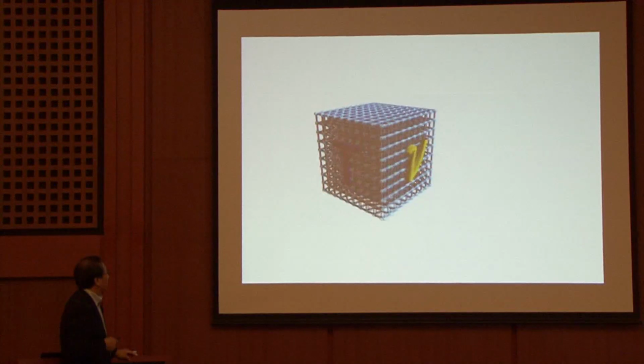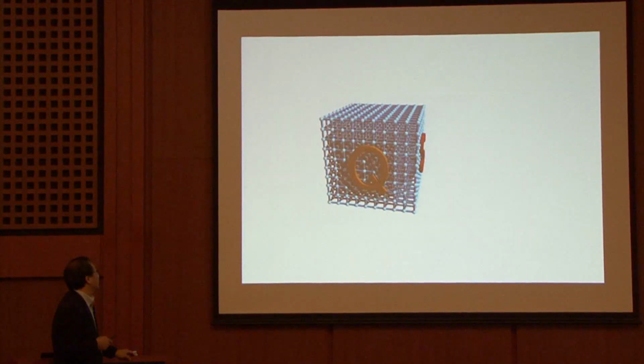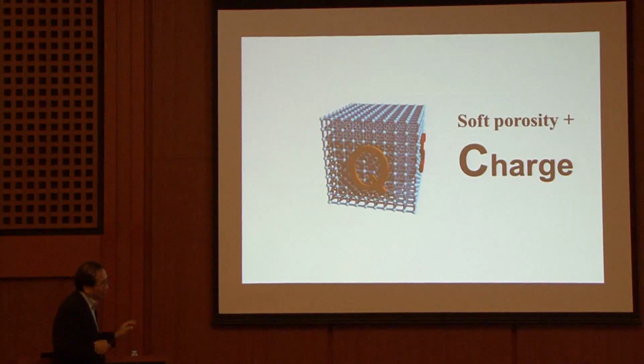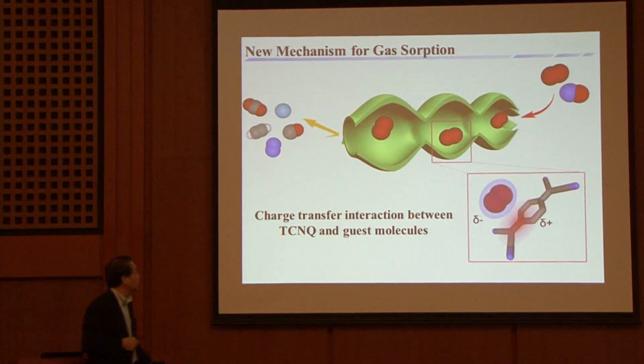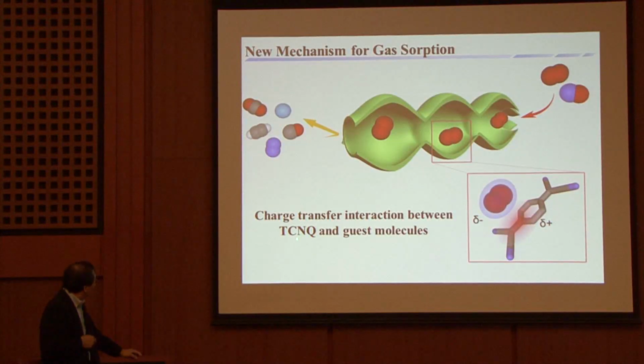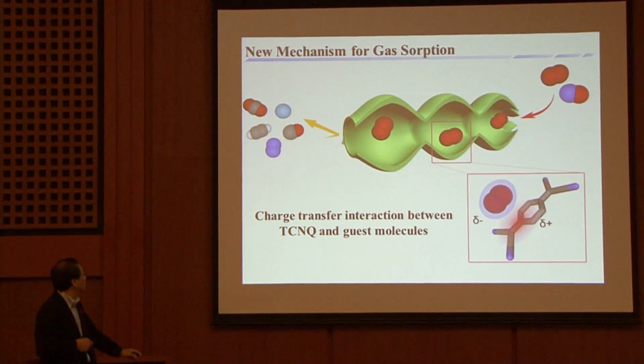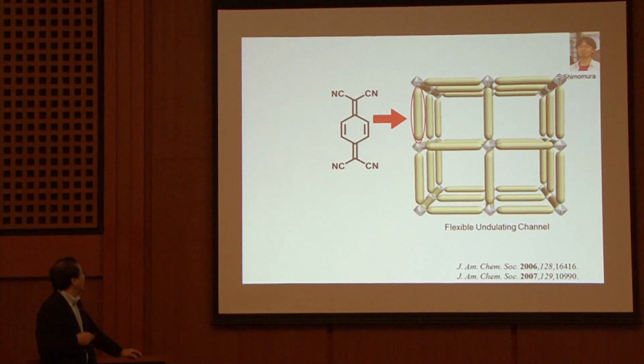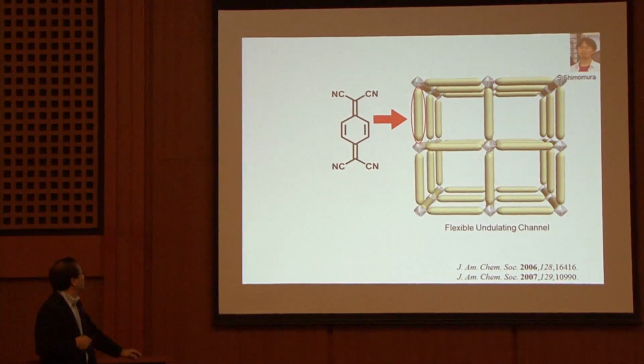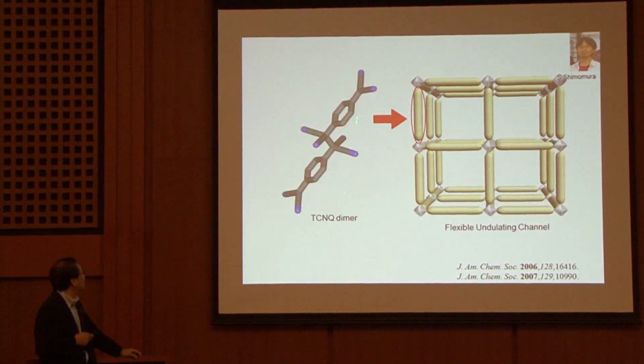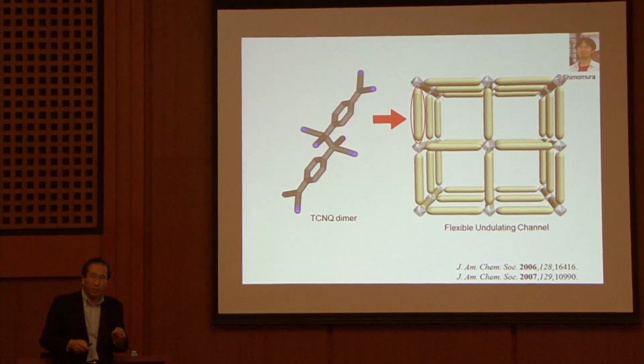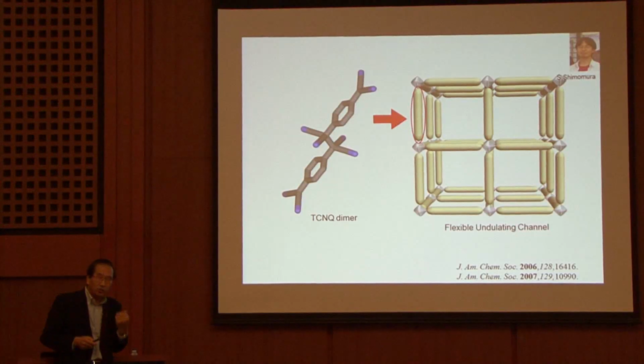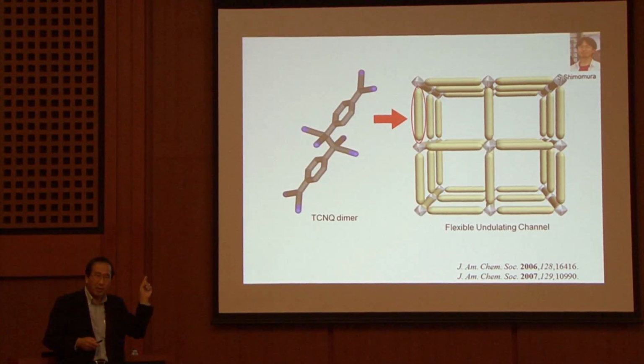The keyword is the charge. That is very interesting. And so let's go to the new type of compound having soft porosity and charge. So we have chosen TCNQ, a very simple molecule, and by using this, we synthesize this type of framework. But accidentally, we obtained this framework from the dimer of TCNQ. TCNQ is famous as an electron withdrawing molecule, but in the case of the dimer, this is TCNQ2 minus. This is very famous as a donor of the ligand electron.